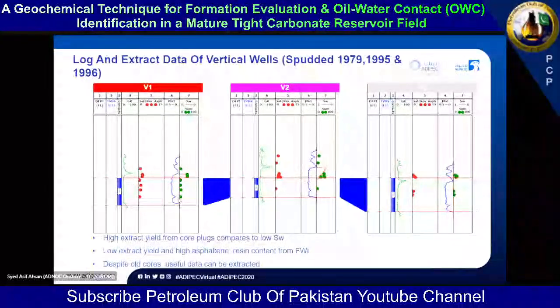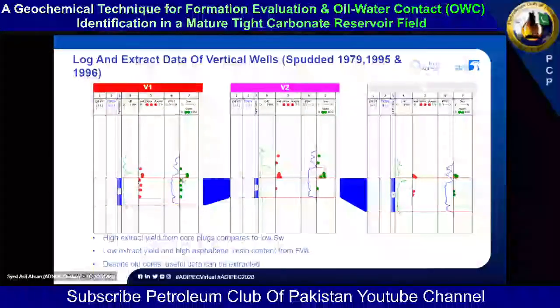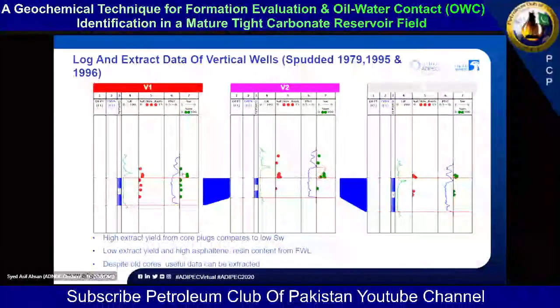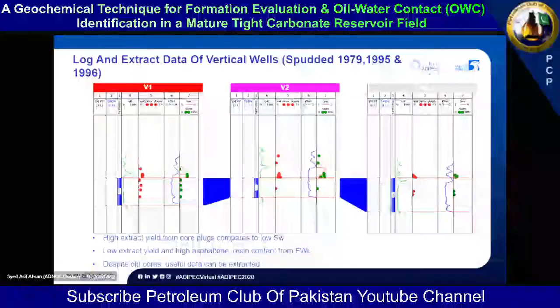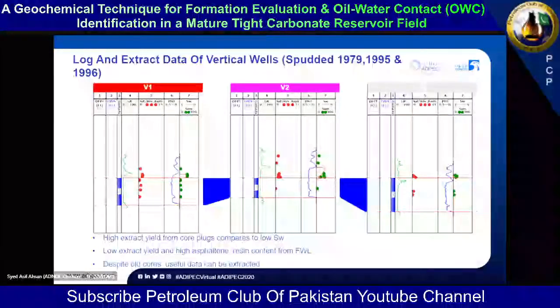So all the core plug samples that came from the free water level have very low extract yield. And above the free water level, the extract yield is high, which is matching nicely to the water saturation derived from petrophysical means, a resistivity-based saturation. And above the main oil zone, there is a dense, non-reservoir layer. And again, there the core was taken, and the core plug extract yield was measured. It is showing low extract yield.